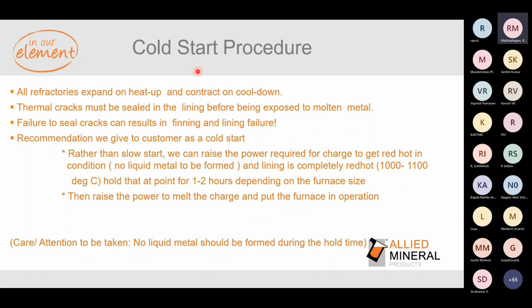Again, coming to cold start procedure. So now you have done a rapid cooling or a slow cooling, but when the furnace is supposed to be restarted again, we need to follow a proper cold start procedure. Cold start procedure is one of the areas where more attention is required for better lining life. Normally, every foundryman follows a slow start after a cool down of the furnace, which is not required. Raise the power so that the charge can be red hot.